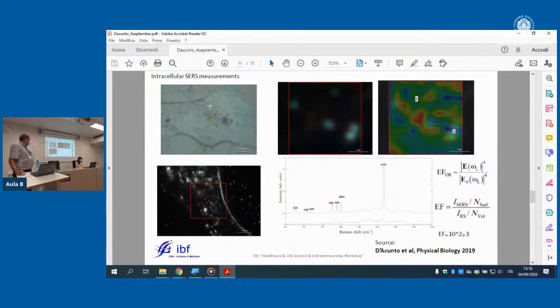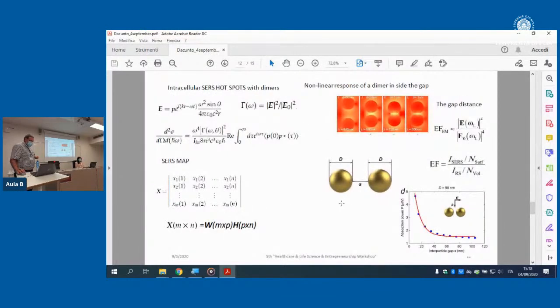Okay, this is focused on a small region inside the nucleus of the cell. And with dark field, you can enhance only the nanoparticle signal, and this is the equivalent Raman map. And we can observe the difference between the non-SERS signal and the SERS signal: we have different bands enhanced by the SERS effect with an increase of about 2 or 3 orders of magnitude.